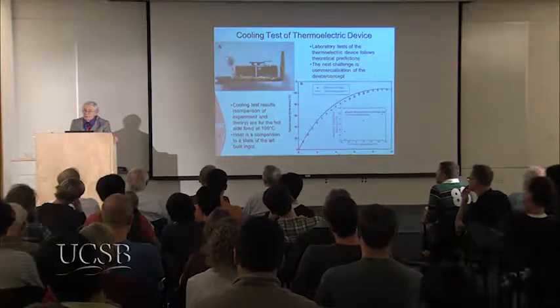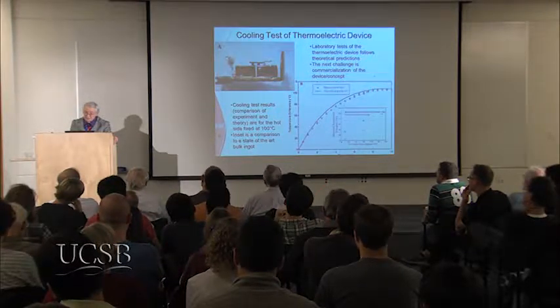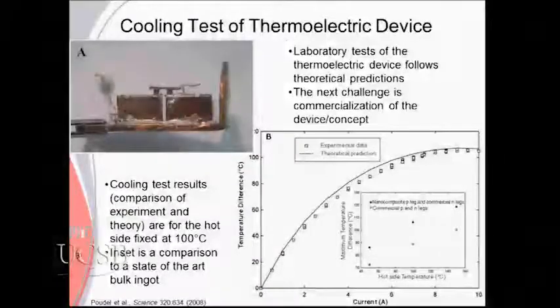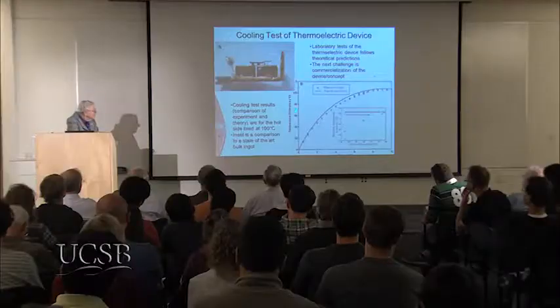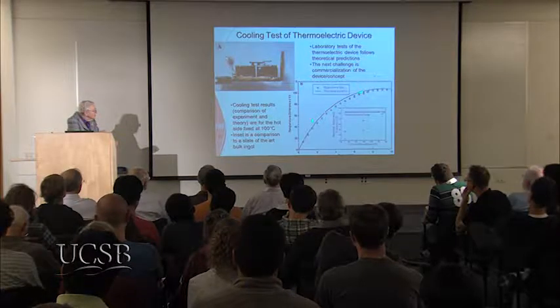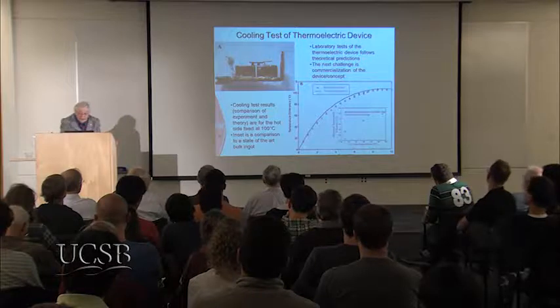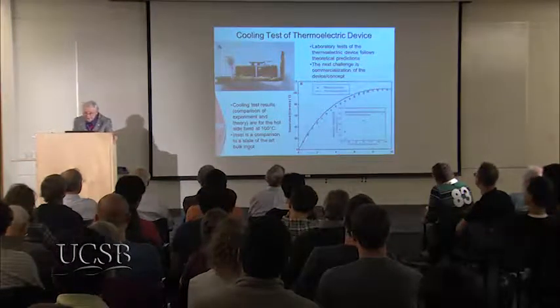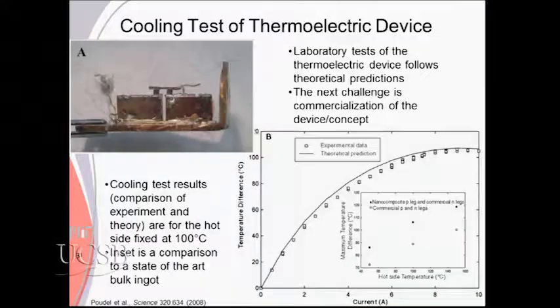Now there's always a test, and the proof of the pudding is that it really cools something by as much as you expect that it would if it had the properties that you said it had. So we know that, and we know how to calculate that. And so if you do something in thermoelectrics, you should normally, at least with one sample, prove that the method that you're using produces the right temperature difference. So here we go. And this is as good as we were in this particular test for that system.